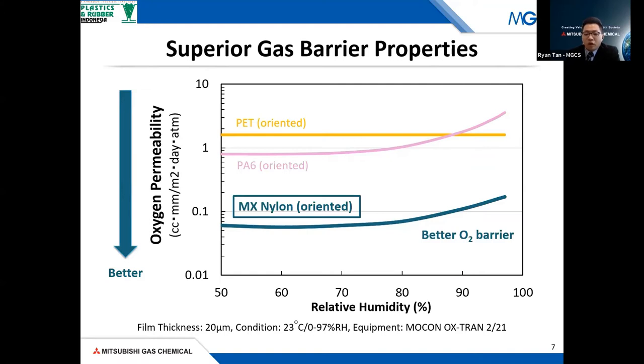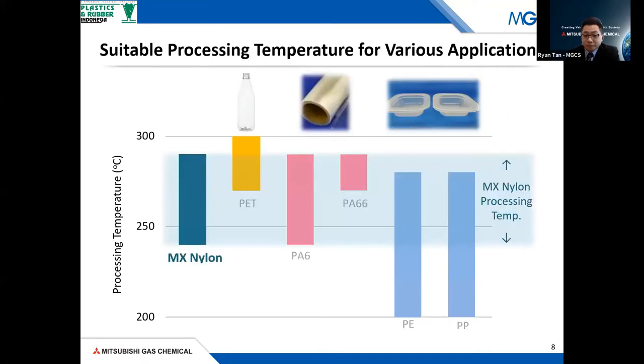So what does all this value mean? Assuming that an oxygen concentration of 10 cc is required for the food to start to turn bad, it would only take about 2 days, mathematically speaking, for food packed in PET to start to turn bad, whereas for food packed in nylon 6, it will take about 10 days. And in MX nylon packaging, it will take more than 3 months. These are all estimates, and the customers will need to perform some tests on their actual product, because different foods are produced differently, prepared differently, and in different environments.